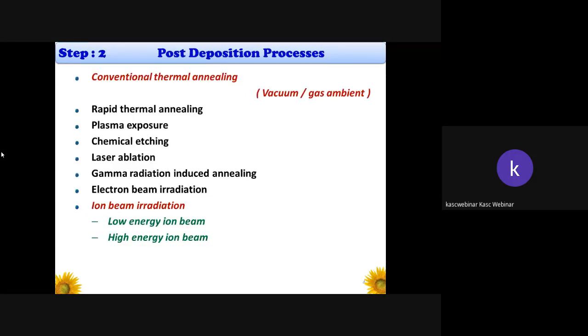Then there may be an intermediate step called the post-deposition process. Once a material has been prepared as an as-grown film, we may expect that the as-grown film itself may be sufficient to prepare the devices. Otherwise, we can go for a certain post-deposition process in order to modify the actual property of a material to suit it better for practical applications. The first and most commonly used is the conventional thermal annealing method. It's a low-cost technique also.